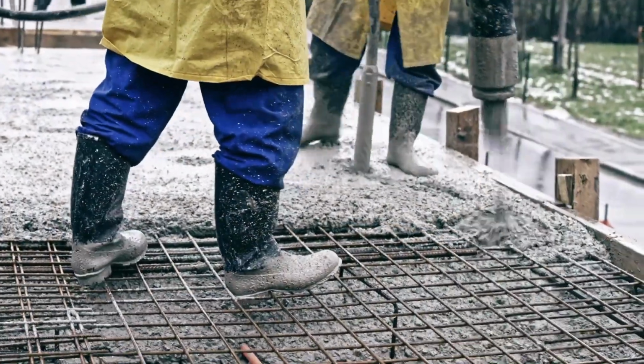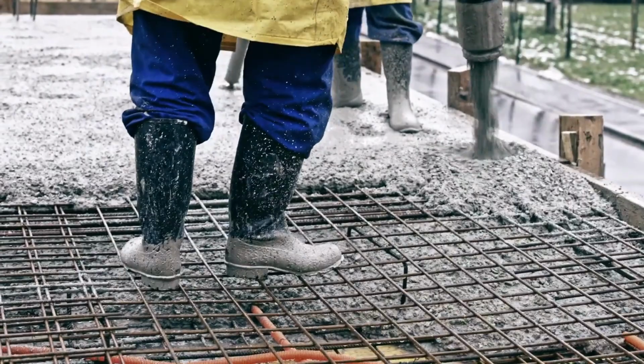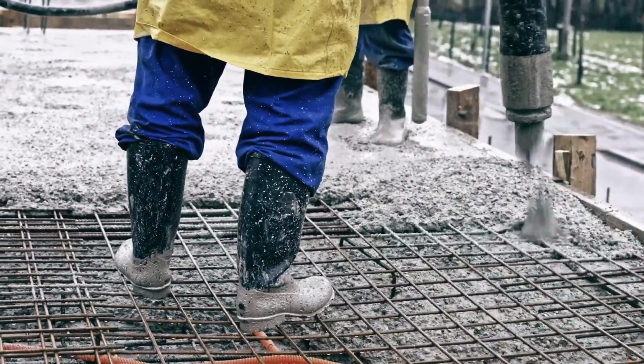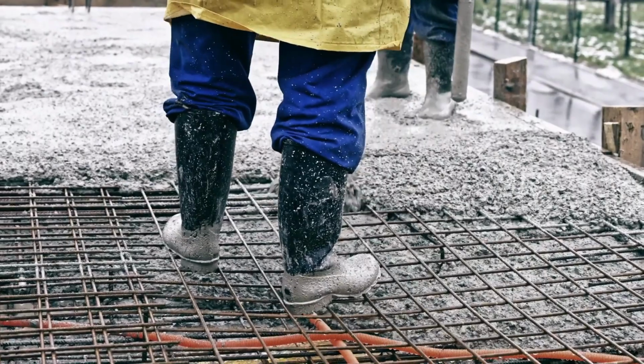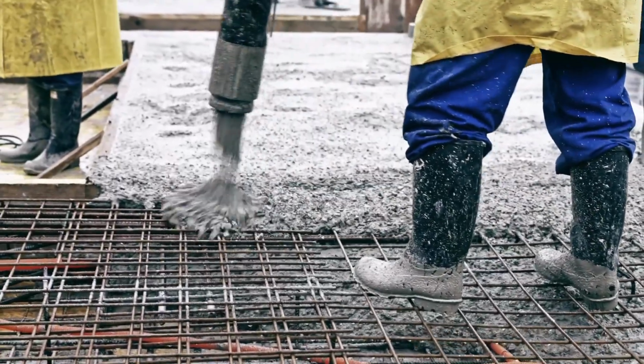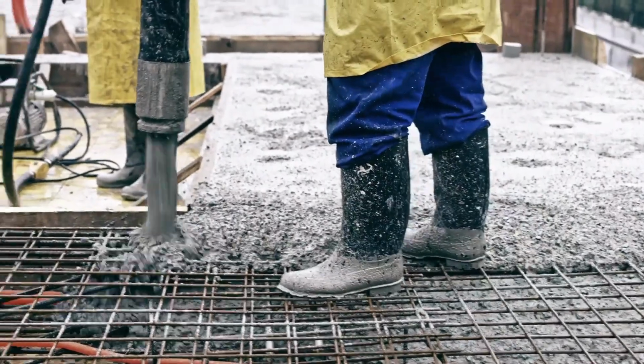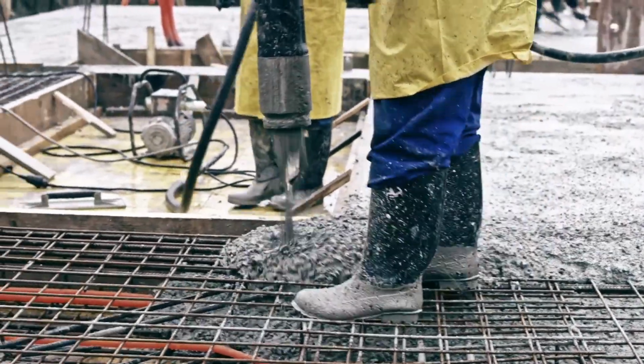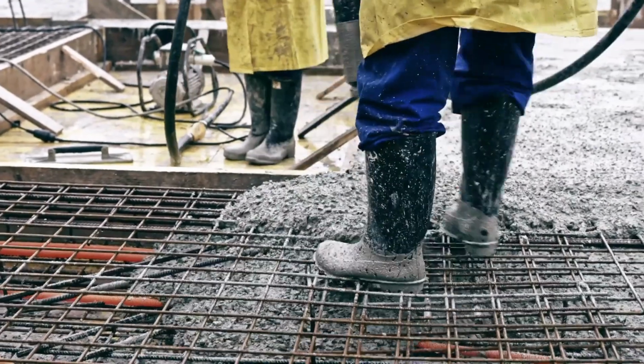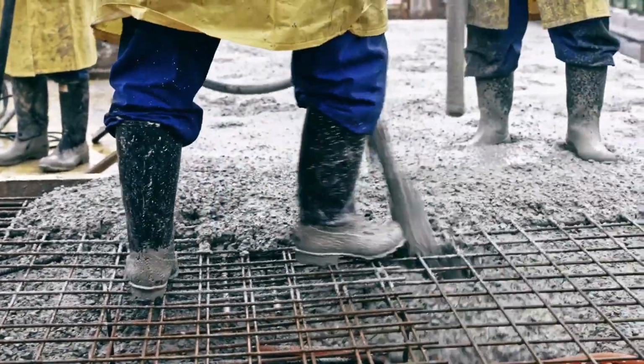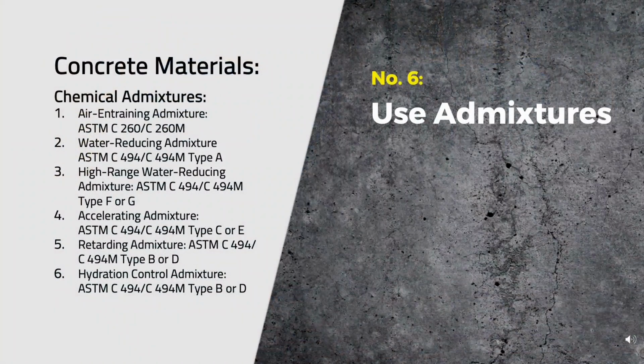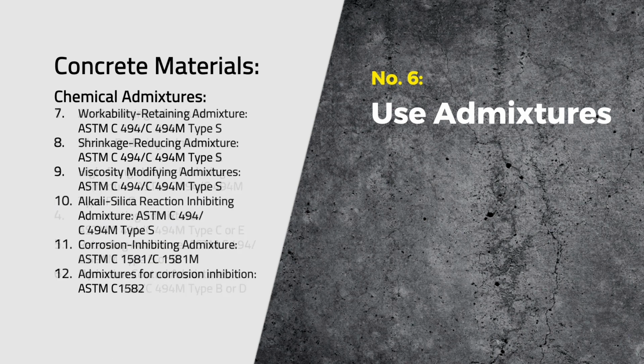As an example of how effective admixtures can be, using a water-reducing admixture that reduces water content in a mixture by 12% will result in a reduction of cement content by 70 pounds, for equivalent slump and strength, and in a carbon reduction of roughly 10% for 4,000 psi concrete. Here is another simple solution. All admixtures that meet an ASTM standard should be permitted and listed in your concrete specification, and those that do not meet a standard should still be considered with proper submittals and technical backup.